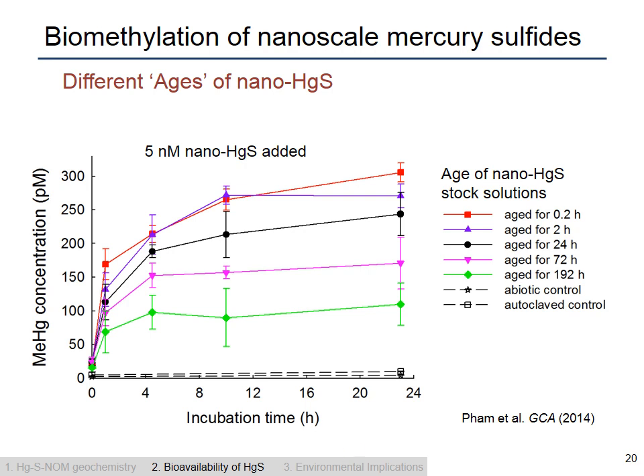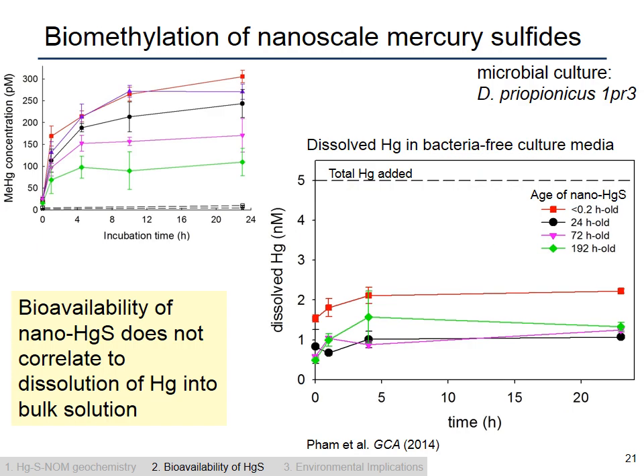So then, this is showing how there's different aging states of nanoparticles, and you can't account for this difference based off of the dissolution of mercury in the bulk water, or at least the quantification of dissolved mercury. So this graph is showing dissolved mercury for different types of nanoscale mercury added to the culture media. And the graph on the left is the same graph I showed before, methylmercury concentration as a function of incubation time for the different aging states.